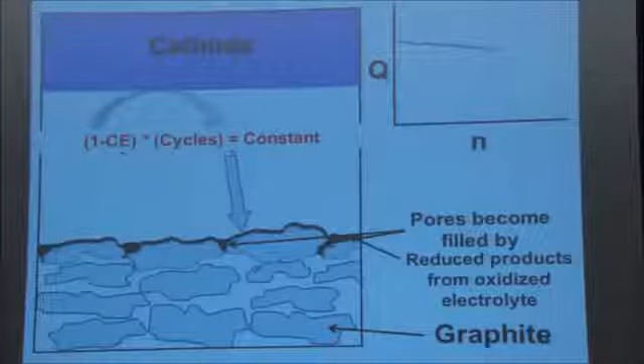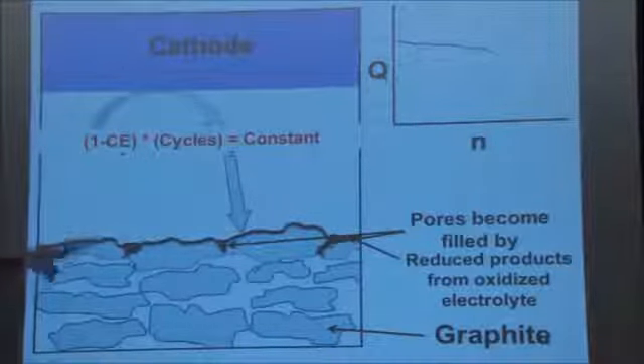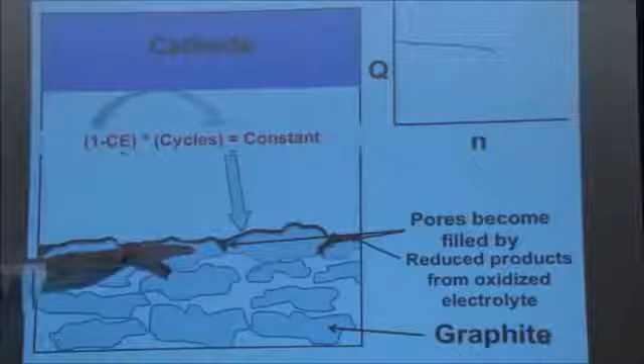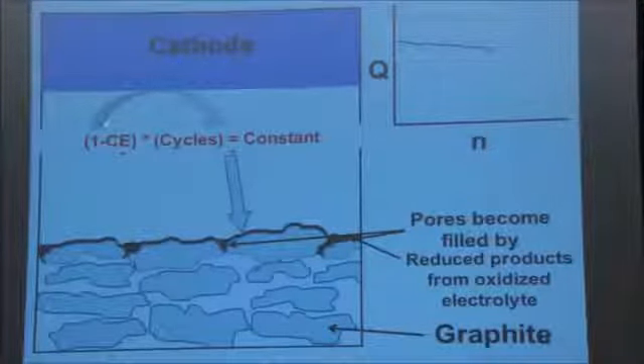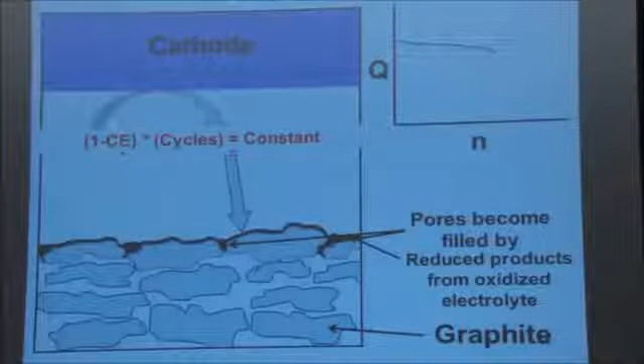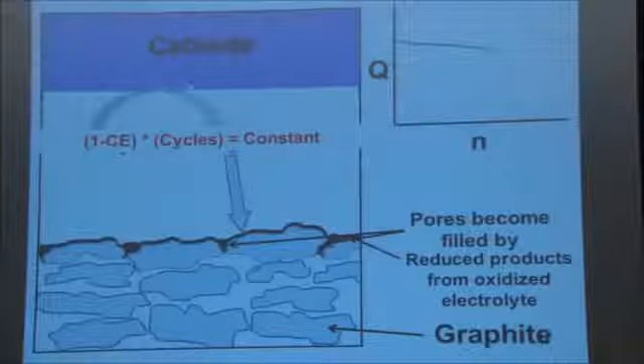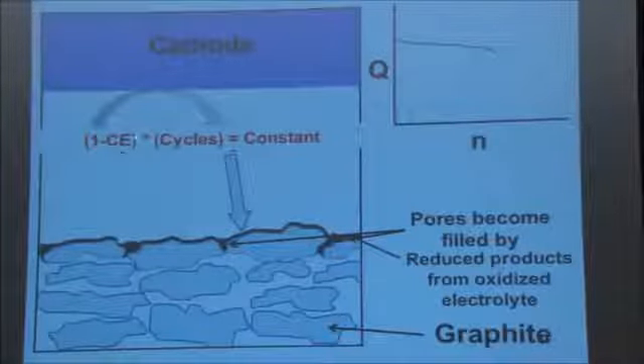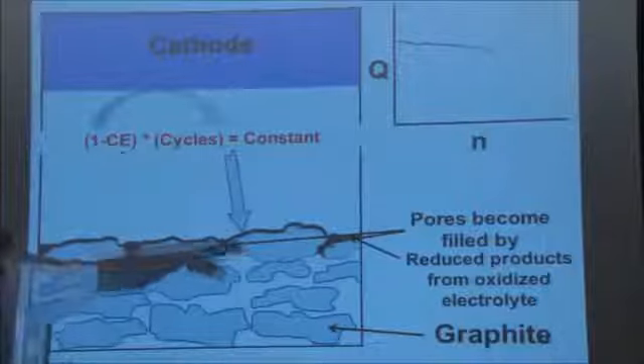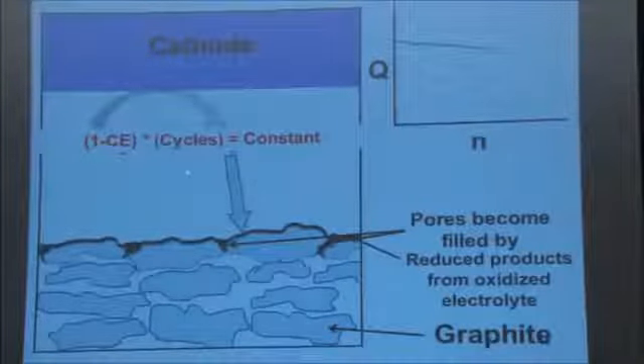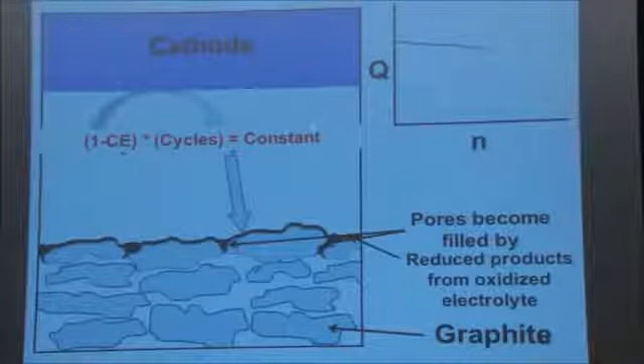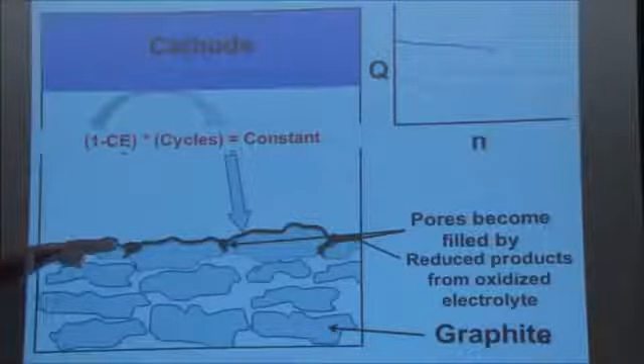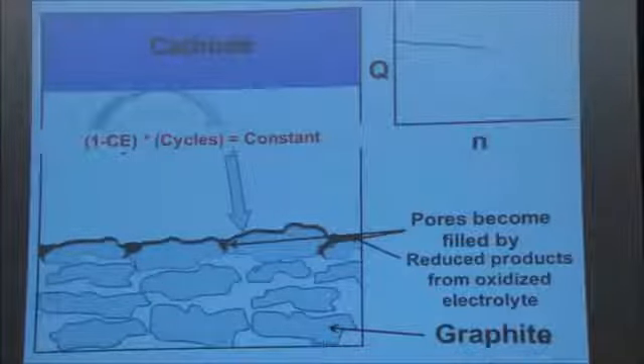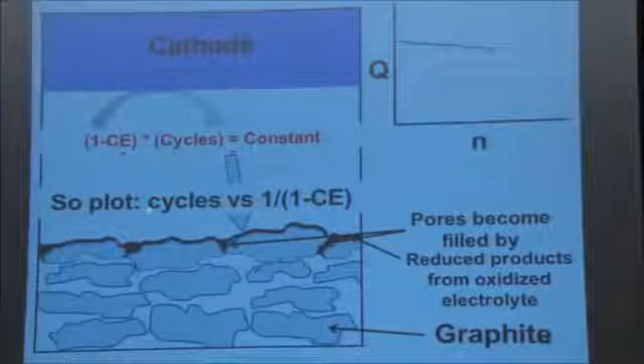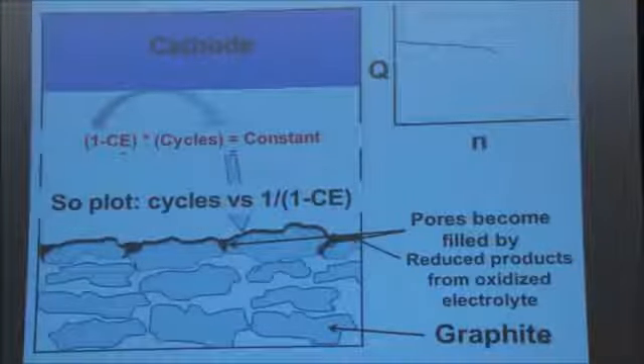Let's say that we need a certain amount of film material to block these pores. And let's say that on every charge-discharge cycle, 1 minus the Coulombic efficiency measures how much electrolyte oxidation products move from one side to the other. Well, if you get this much material on every cycle, and you need a constant amount of material to block the pores, then 1 minus CE times the number of cycles to failure should be a constant. And this constant is going to be proportional to the thickness of the film needed to block those pores. So what you need to do is plot a graph of the number of cycles to failure versus 1 over 1 minus the CE and see what you get.